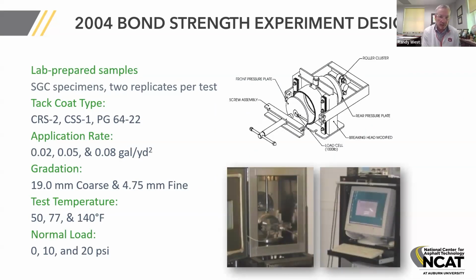We prepared gyratory specimens, did 2 replicates per test. We used 3 different types of tack coat, 2 emulsions and 1 PG binder. We ran 3 different application rates. We did mixes with a 19 millimeter coarse mix and a fine 4.75 millimeter mix on both the upper and lower layers. We did 3 different test temperatures, and we did 3 different normal loads. That's the load being applied to the face of the specimens as the shearing is occurring during the test.